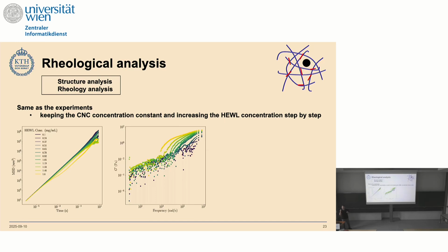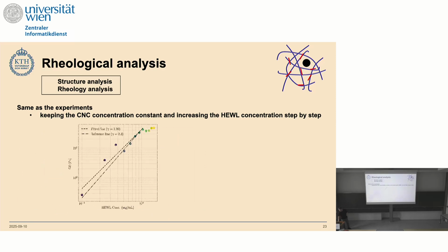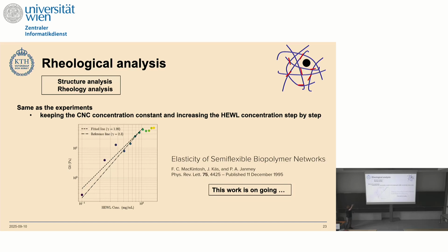So in the coacervate phase, we added a bead to diffuse into the system and get the rheological behavior. We were able to compare it with some of the reported results in the literature. They connect the G0, or the plateau region of the rheological behavior, with the concentration of the biopolymer.